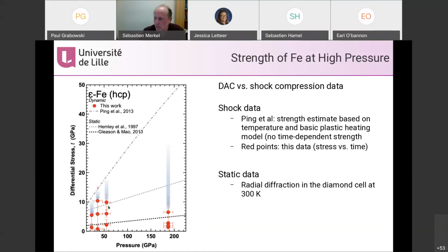And then our data points, the stress values we measured, plot closer to what was measured in static experiments. Now, as I said, maybe the peak stress at the onset of plastic flow is higher than what we measure, but a few nanoseconds later, this is where we are.